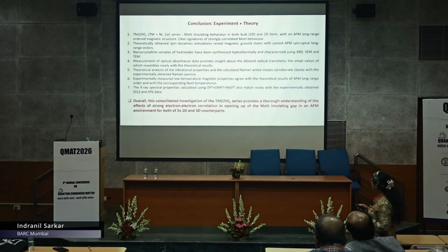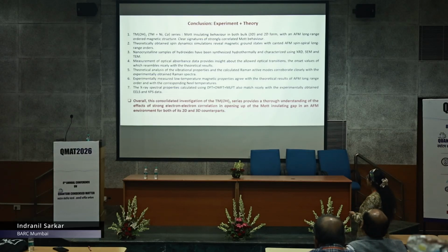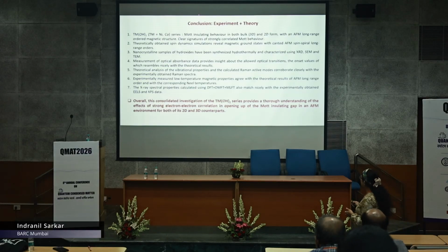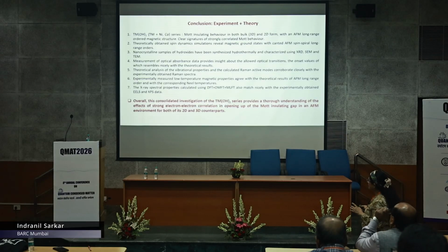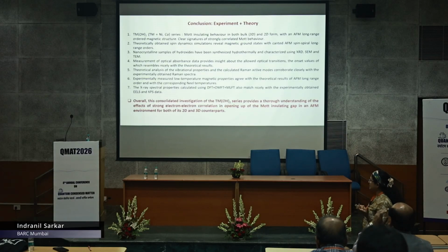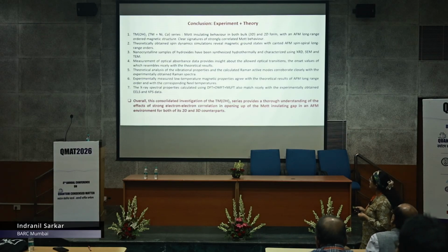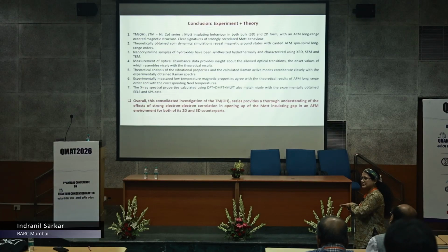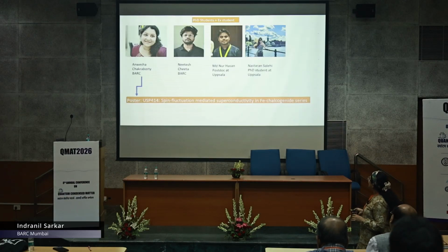So our conclusion from theory and experiment, from this consolidated investigation, is that the TM(OH)2 series, both its 2D and 3D counterparts, has an antiferromagnetic insulating behavior, and it is one of the very rare classes where the 3D Mott insulating behavior extrapolates into 2D.